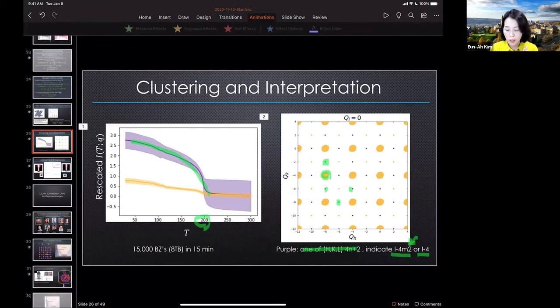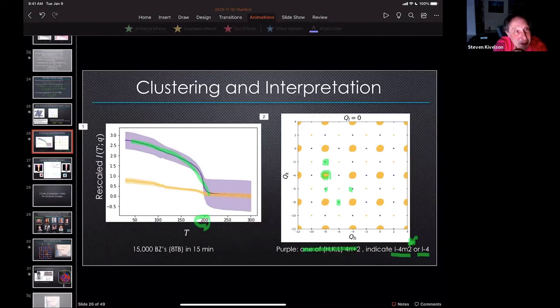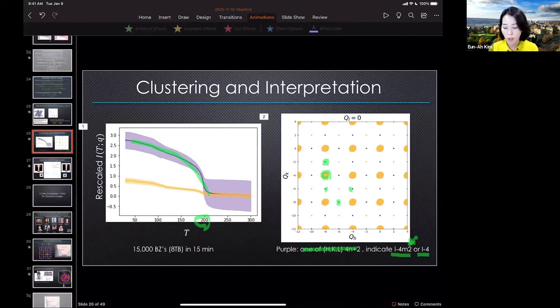In principle, though, just from the positions of the Bragg peaks, you should be able to tell what the symmetry is. It's just that they're very small distortions. Right. The positions of the Bragg peaks, we know the lattice constants, and the lattice constants are not changing. Some of the Bragg peaks that were not visible at higher temperature become visible, so they are symmetry allowed or disallowed. That still leaves a whole host of possibilities. It does not narrow down uniquely.